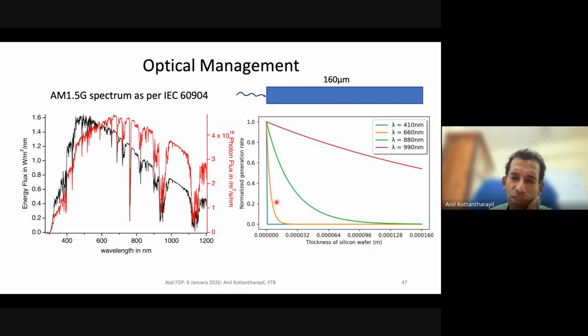Maybe you can see that the absorption coefficient is very high for short wavelength light, right? This is UV, for example, and then visible range also gets absorbed within a very short distance. This is the thickness of the silicon wafer in meters. So this is about 160 micrometers. Within a few micrometers or tens of micrometers, this visible light gets absorbed, and infrared, you can see as the wavelength increases, not all of that light actually can be absorbed in 160 micron thickness of the silicon wafer. Why 160? Because that is close to what is being used in the industry today. So industry currently uses about 130 micrometer thick silicon for making solar cells.